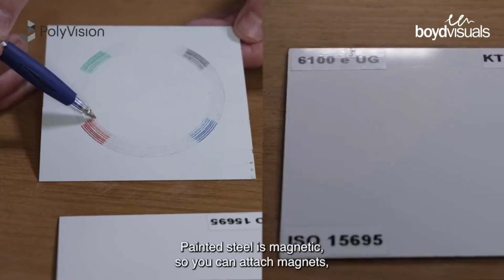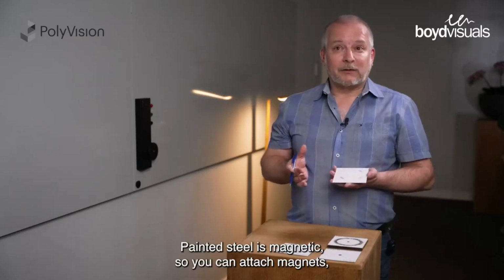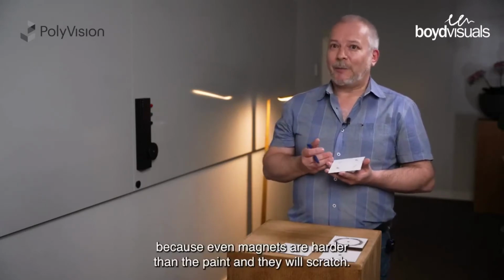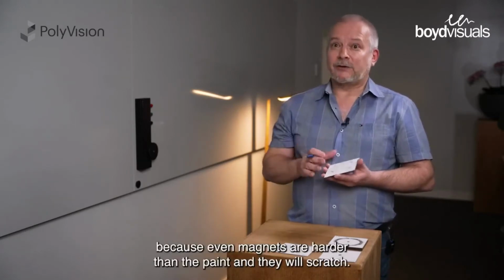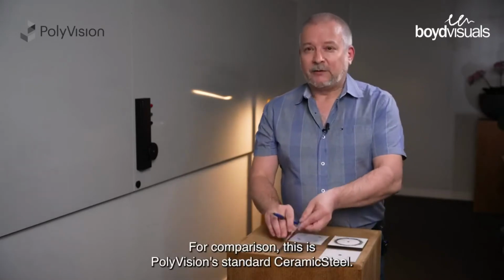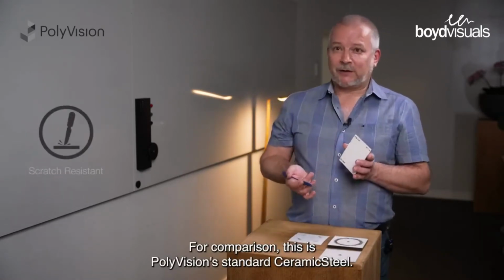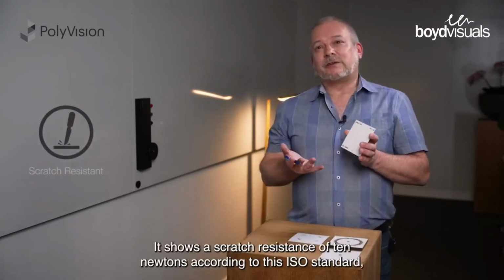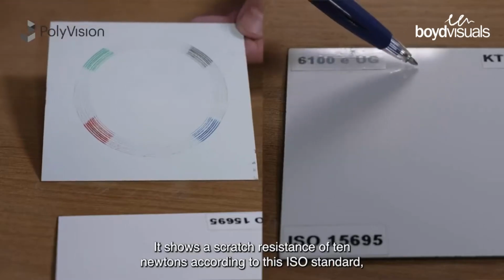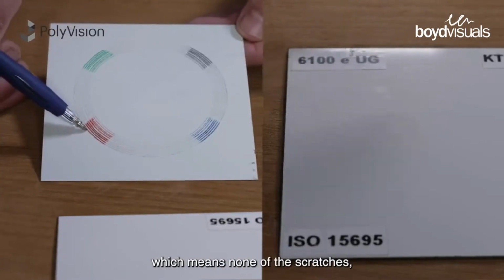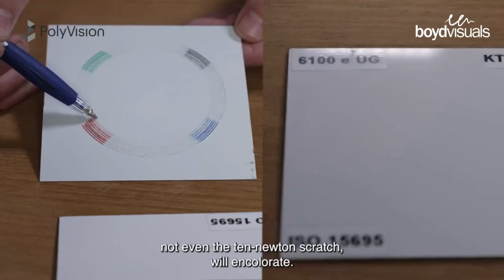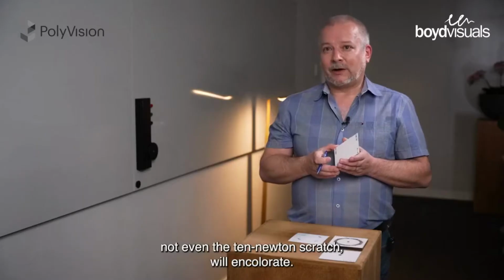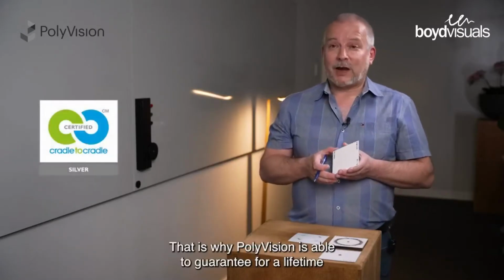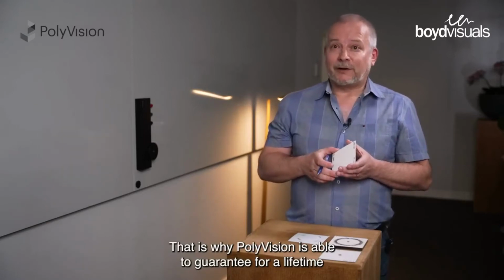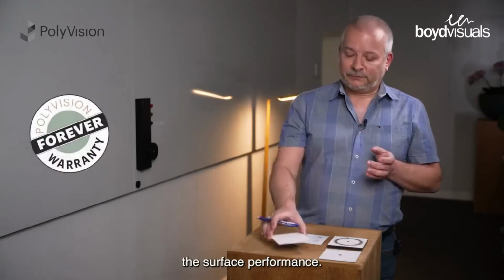Painted steel is magnetic, so you can attach magnets, but you need to be very careful with that, because even magnets are harder than the paint and they will scratch. For comparison, this is Polyvision standard ceramic steel. It shows a scratch resistance of 10 newtons according to this ISO standard, which means none of the scratches, not even the 10 Newton scratch, will incolorate. And that is why Polyvision is able to guarantee for a lifetime the surface performance.